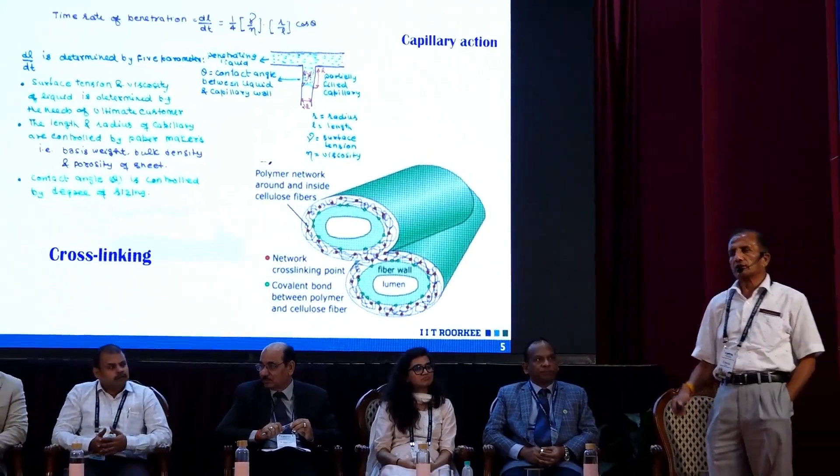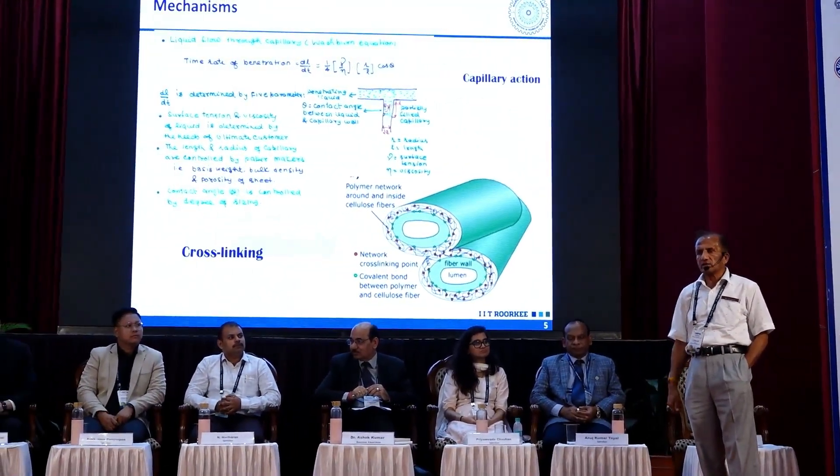What is the fundamental difference between paper and polyethylene chemically? In the case of plastic and polyethylene, it has covalent bonds, whereas in the case of paper it contains hydrogen bonds — more than 60% of the bonds in paper are hydrogen bonds. Second, in polyethylene or plastic there are no side chain groups or functional groups, whereas paper contains hydroxyl groups. So, if we are able to protect these hydrogen bonds in paper, then we can develop barrier properties.